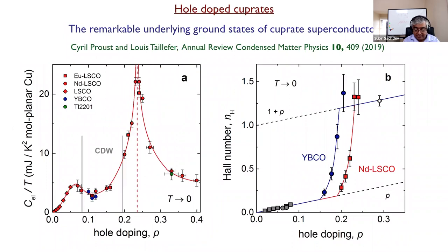I also show here some other data. This is a bit older, but only by a couple of years. If you measure the gamma value of the specific heat, C over T, this would be just related to the effective mass of the quasi-particles on the Fermi surface for a circular Fermi surface. And that seems to have a big peak right at the critical doping, where you go from p greater than pc to p less than pc. And if you measure the Hall effect, this is in high fields, you again see, consistent with the very simple-minded picture, density p here and 1 plus p here.